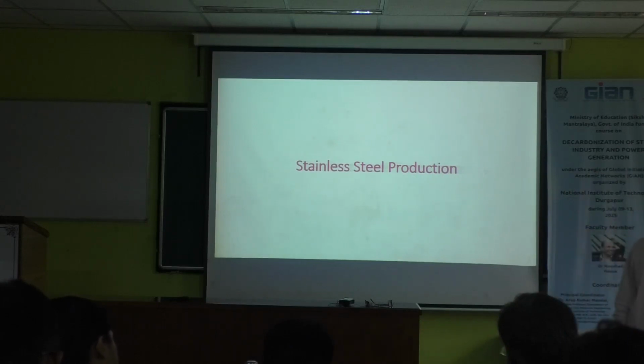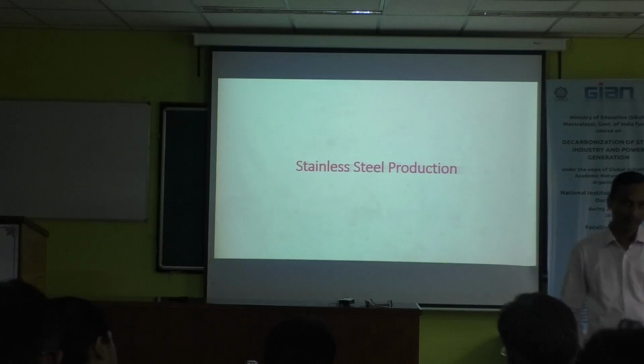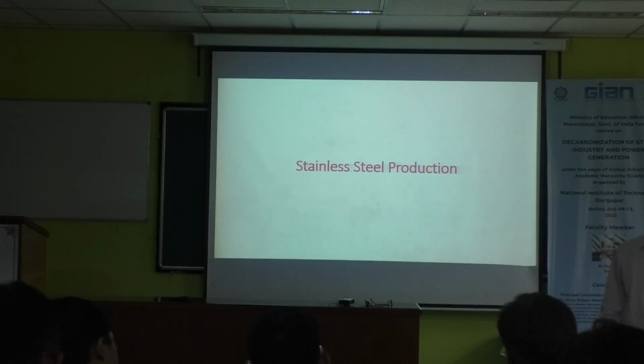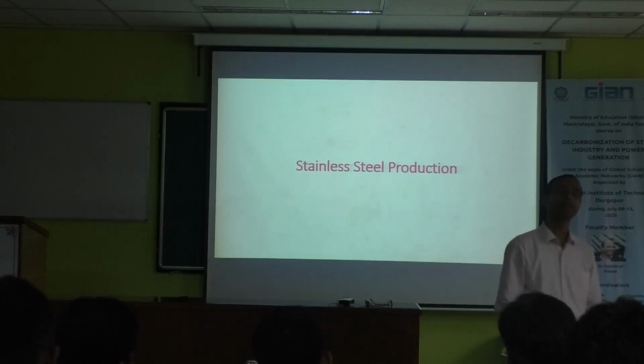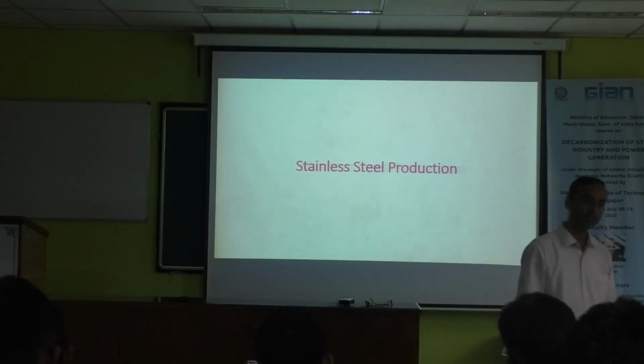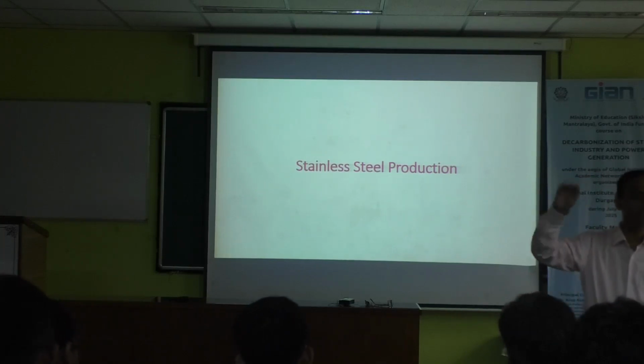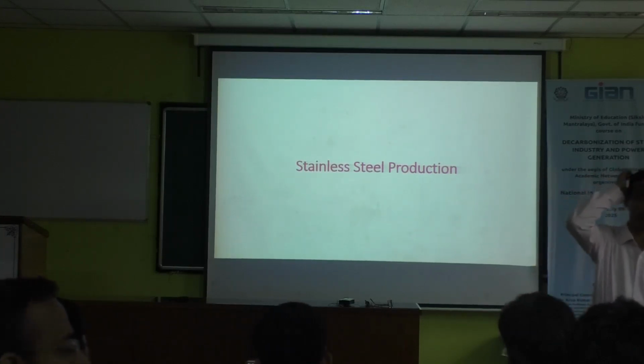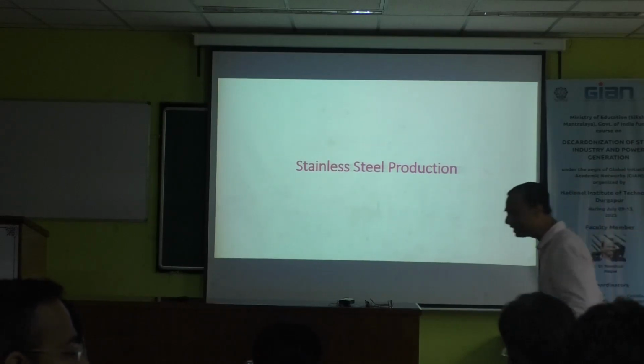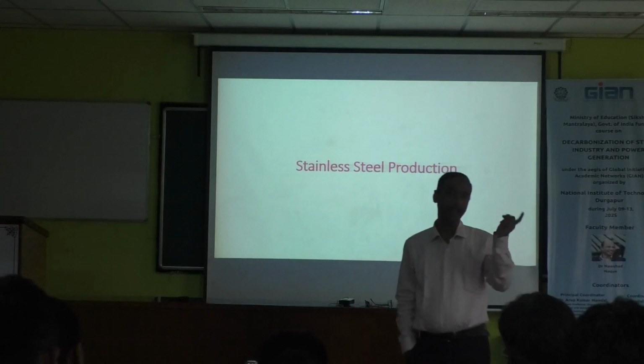Then another requirement is chromium and nickel. In the Indian context, we don't have nickel, so we are dependent on other countries to get nickel. Then there is a lot of research, I think Promodar is familiar, on nitrogen bearing stainless steel, in which nitrogen will replace the nickel content. But how much? Near normal atmosphere, you can easily introduce 4,000 ppm. It depends upon the chromium equivalent and nickel equivalent.